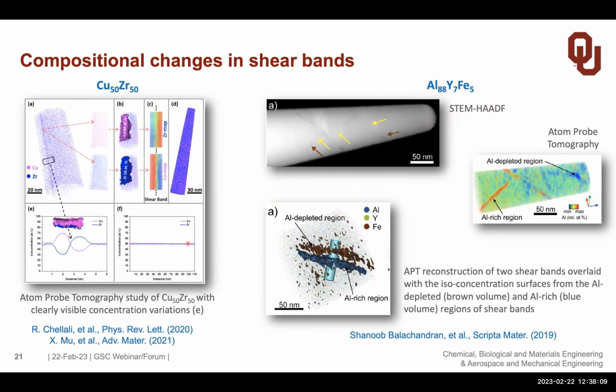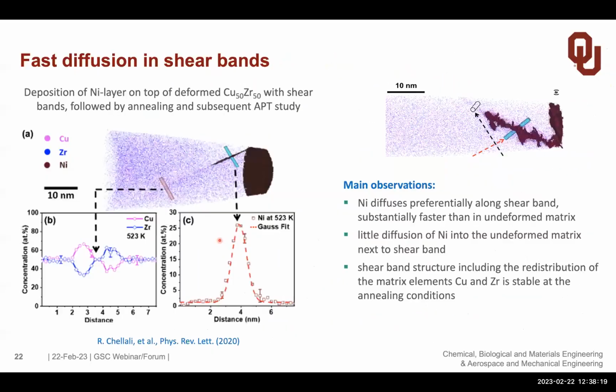Aside from the shear band, it's homogeneous. So we have a homogeneous composition outside the shear band, and in the shear band we get a very drastic change of the composition and of many other things. So now I thought, let's look at how a property, in this case the diffusivity, is affected. So we put a little bit of nickel on top of the copper zirconium, and then we looked at the diffusion of the nickel. It only diffuses in the shear band. It doesn't diffuse left and right at that temperature. It only diffuses here. This is orders of magnitude of difference in the diffusivity, the mobility of the nickel atoms in the shear band.